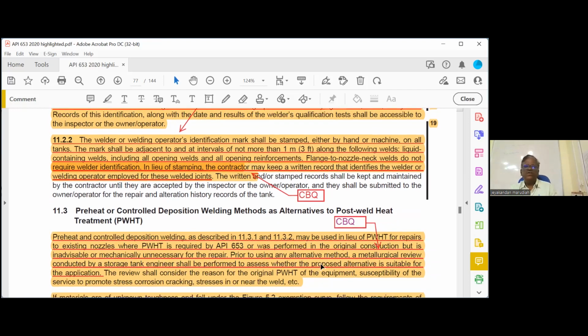Now we will go to what is meant by the preheat method and what is meant by the controlled deposition method. Even though it is not very important for the exam, maybe one question only. Now, understand, a tank was furnace stress relieved originally as per construction. What requires post weld heat treatment? Shell clean-out openings plus stiffeners, PWHT is required. Group 1 to 3, nozzle size more than 12 inch, thickness more than 1 inch. Group 4 to 6, nozzle size more than 2 inch, thickness more than half an inch.